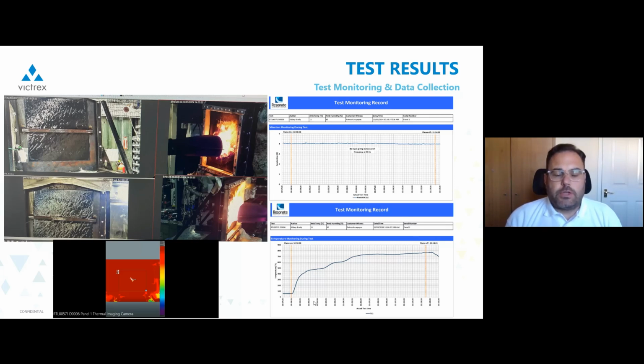pictures. So you actually have feed from the front camera where the conical burner is, and you see the flames. And then you also have a picture at the back. This is actually the most important camera, because that will show you if you have penetration and when that happened, because again, there is a timer that's going on. At the bottom, what you see in red is one snapshot from the thermal camera.